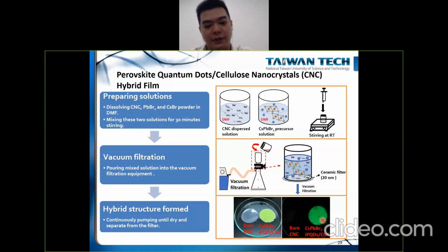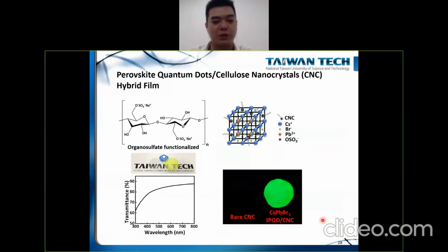So what's different between this and the traditionally used capping ligand? It should be noted that for this type of procedure, we did not add any traditional capping ligand such as OA or OLA. And without the quantum dots, you can see the CNC film is actually highly transparent, with over 80% transmittance in the visible light region.